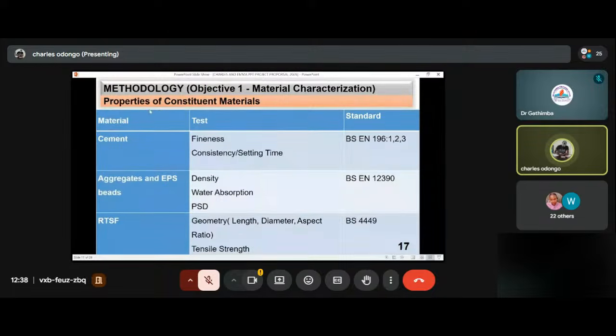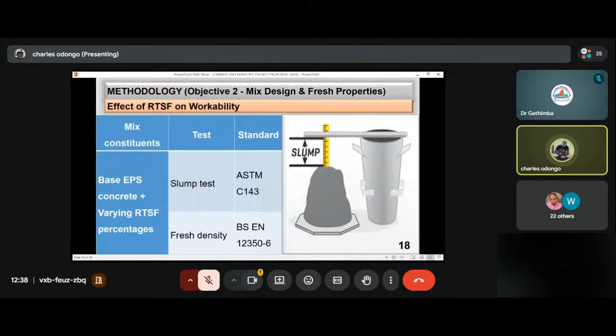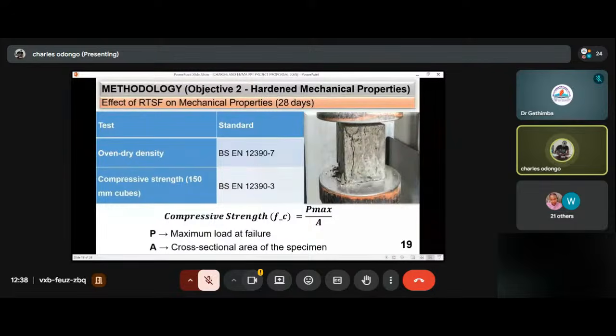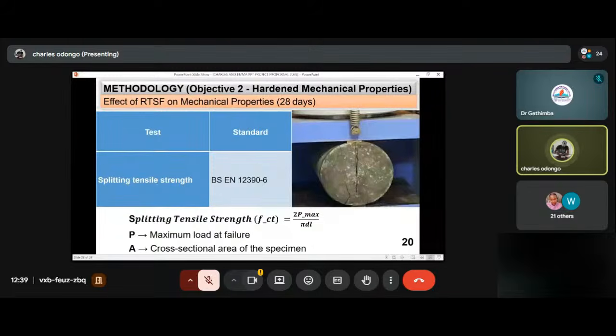On objective one, material characterization, we will do some tests on cement, on the aggregates and RTSF. For instance, on the aggregates, we have to do density, water absorption, and PSD, which will give us the properties of these materials. Going to objective two, the mix design and fresh properties, we'll do the slump test after mixing the varying percentages of RTSF and also give the fresh density of this. Then we'll also do an oven-dry density after doing the wet density. Still under objective two, for the hardened mechanical properties, we'll do the compressive strength and the splitting tensile strength, and the formulas are indicated as I have shown.